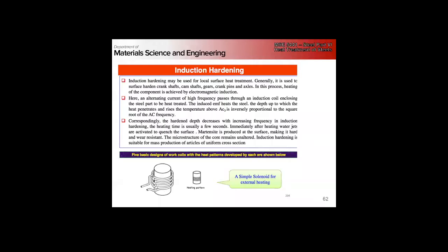Where you can use induction heating on a very localized region to heat it up, right? And this is a really convenient way of hardening certain surfaces on crankshafts, pins, right? Anything where you need, any rotational part where you need local hardness, right? We can do induction heating and then quench, right? And it's very fast, right? Right, it's really a mass-produced thing.